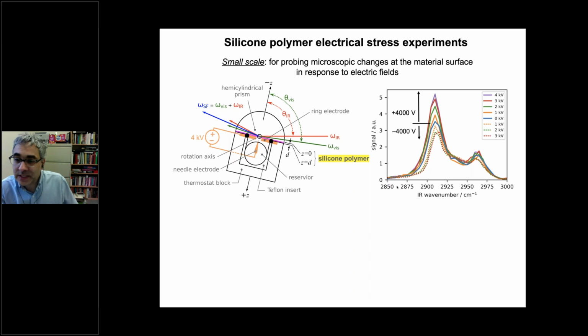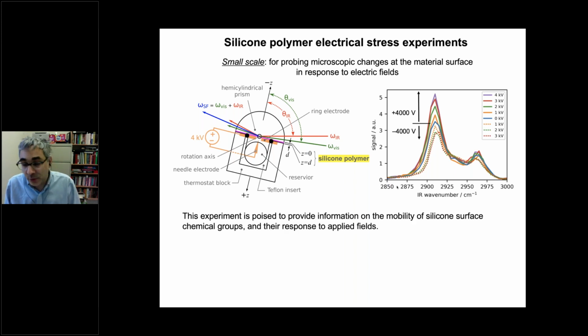And the more we study this phenomenon, we have a very different kind of molecular picture as to what's going on. It's much more of a dynamic picture where these chemical functional groups are flipping back and forth very rapidly. And then over time, as the material ages, just like our bodies, like our elbows and our knees when we get older, we're not able to go through that full range of motion anymore, and it kind of slows down because there's so much motion that happens in these pristine materials on the microscopic scale. So we're really interested in these experiments, and they're really poised to provide information on the mobility of these surface functional groups.